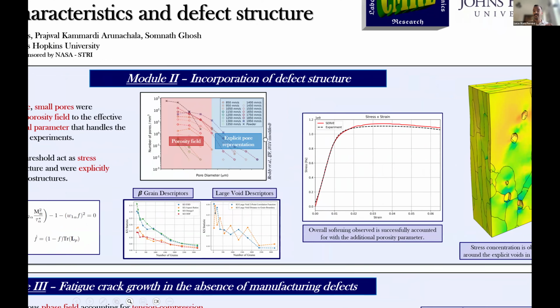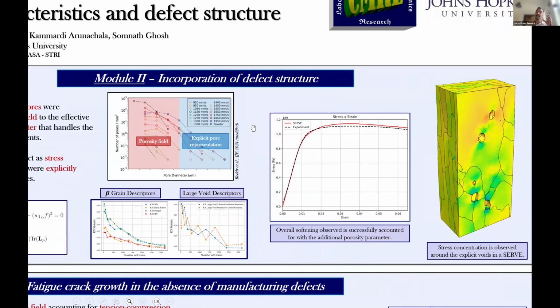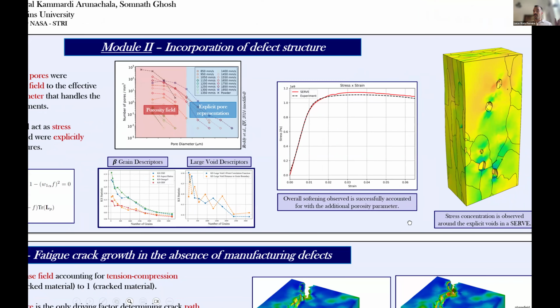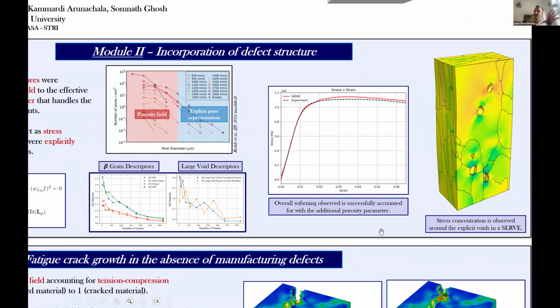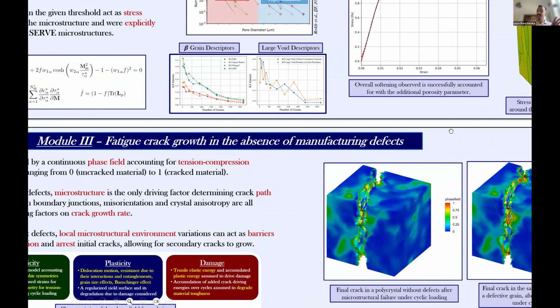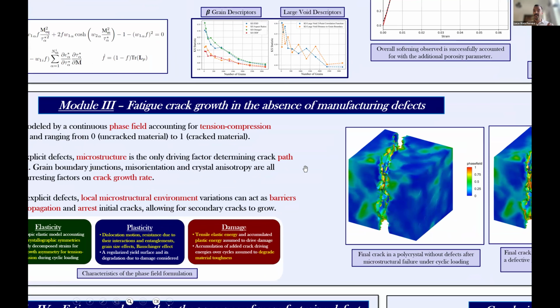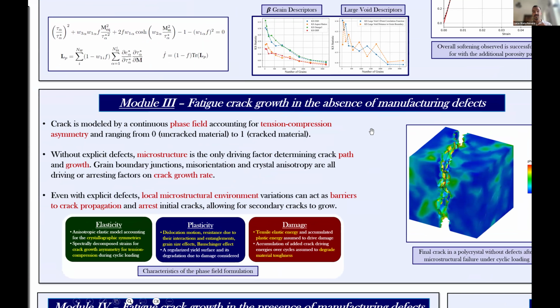On the other hand, when the defects are large and can be pointy, so they mostly act as stress concentrators, we decide to explicitly embed them in our statistically equivalent RVE, so that they can actually act as stress concentrators as we know them. Once we have this framework of the microstructure and defects, we can track the crack propagation. We use the phase field formulation that takes into account the difference in tension and compression, the asymmetry, and all the characteristics for elasticity, plasticity, and damage evolution.